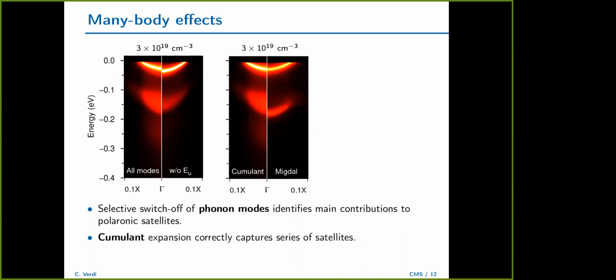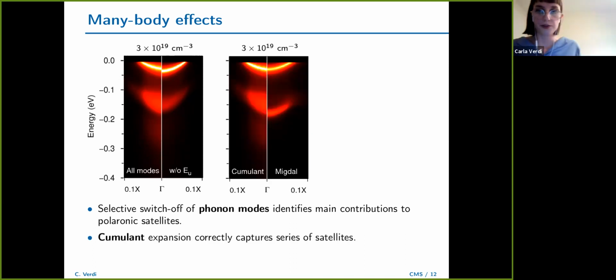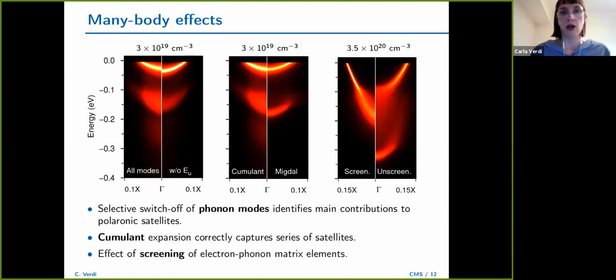So another interesting comparison is between the spectral function that you calculate from the cumulant expansion and from the Migdal approximation. It's similar to what I showed you before in an angle-integrated spectrum. Here you see that with the Migdal approximation, the satellite occurs at a much lower energy, and you can only ever capture one satellite within the Migdal approximation.